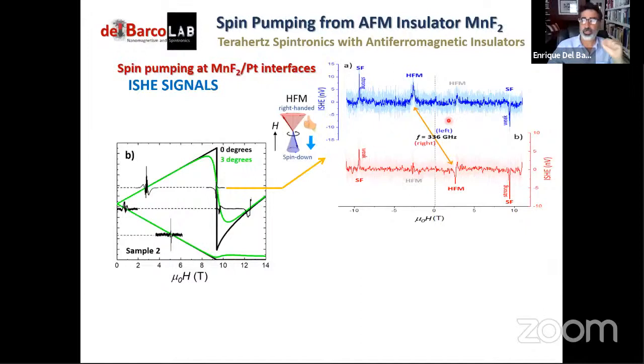And if you pay attention to what happens here with the main feature that corresponds to the high frequency mode, it gives a dip in voltage for positive fields. It kind of disappears here. Also, there's a little bit of evidence there. But then it gives a peak of voltage, a positive voltage, when we reverse the magnetic field, negative magnetic fields. But we also reverse the circular polarization of the microwaves. So we have this correspondence, a feature that we see here, but we don't see across, right? And then we are also observing some differences in the spin flop transition peak that I don't want to discuss right now. We'll get back to this later.